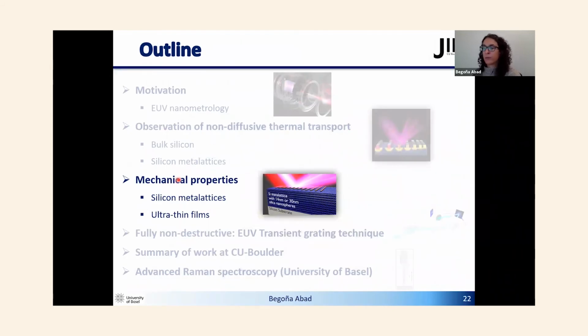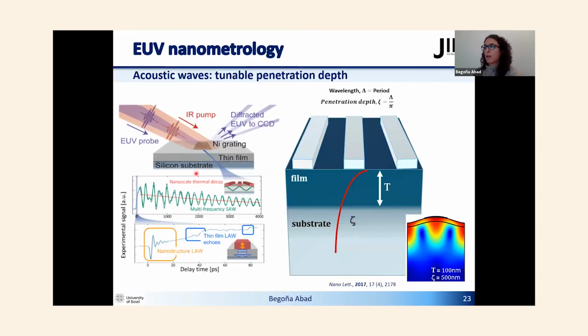Okay, so now I move to the mechanical properties of these silicon metalattices and also of ultrathin films. Before I explain this technique, I want to focus more on the acoustic waves part. One of the very important things of this technique is that we are able to tune the penetration depth of our waves just by tuning the period of these gratings. That is, the acoustic wave has a wavelength that is given by the period, and the penetration depth is just the period over pi.